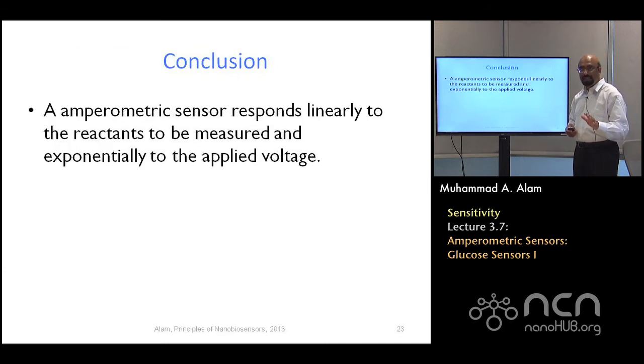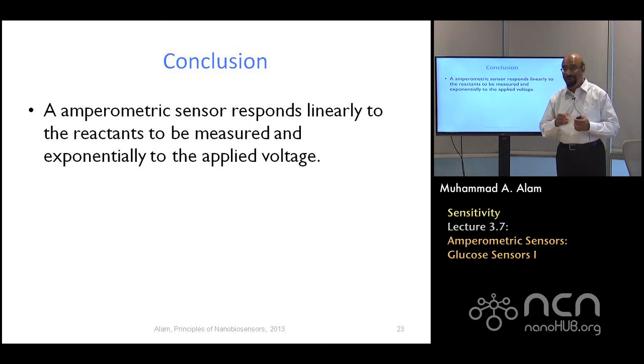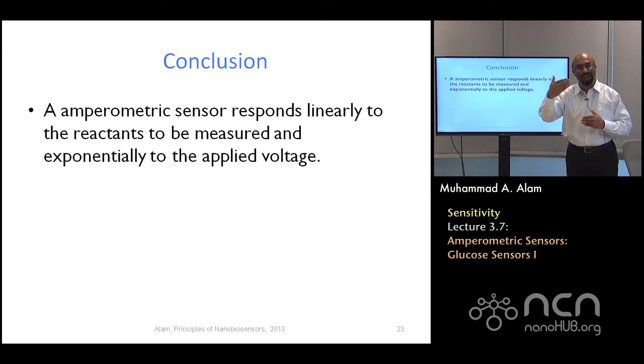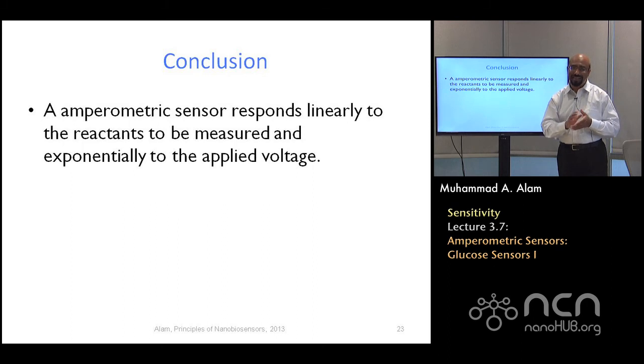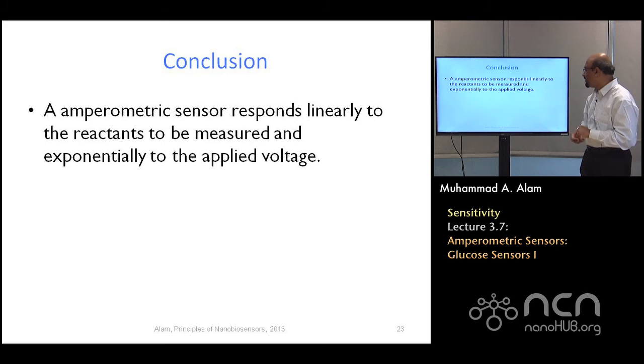So let me conclude this first lecture on the amperometric sensors by summarizing a few things. As I said, the amperometric sensors essentially respond linearly to the reactants to be measured. Remember that for potentiometric sensors, it became a log because of the screening. Fortunately here, if you increase the concentration by a factor of 100, you do get a factor of 100 increase in the current. That's pretty good compared to what happened in the potentiometric sensors.